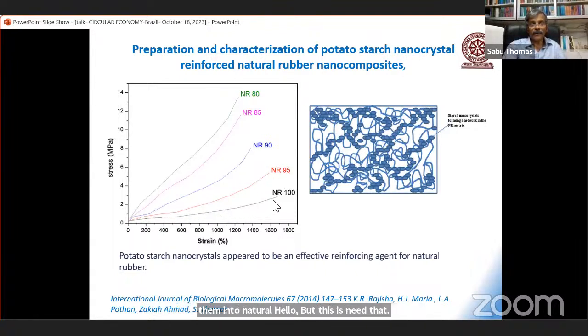Look at this. By putting 5, 10, 15, and 20% of nano starch, you see, natural rubber is transformed into a high modulus material. Rubber is very, very flexible. You can see the flexibility is reduced and it becomes a very strong material. And the strength and modulus of natural rubber has been increased quite dramatically.